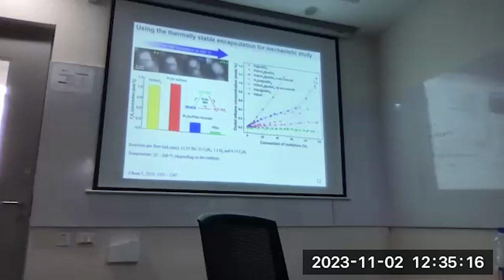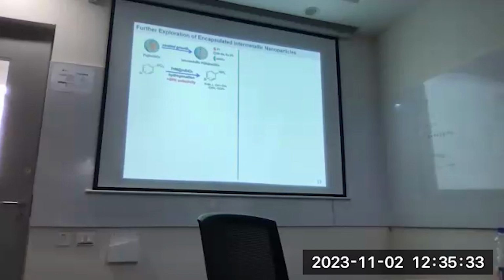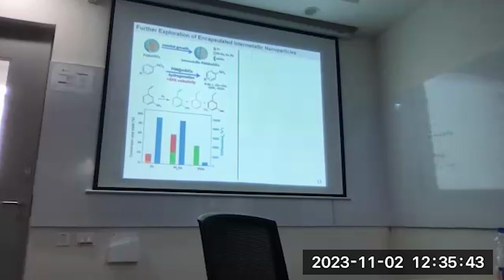So again, with these intermetallic compounds, basically you isolate the most active component and then try to push it towards selectivity. Now, most of the reactions I've shown are very simple, but there are applications where you can divert the selectivity to a completely different product. So then we tried this other reaction with nitrostyrene, and we used the same explanation that we used for the alcohol, again, the mode of adsorption. And we could selectively get this compound.